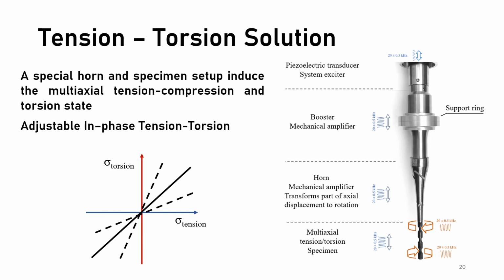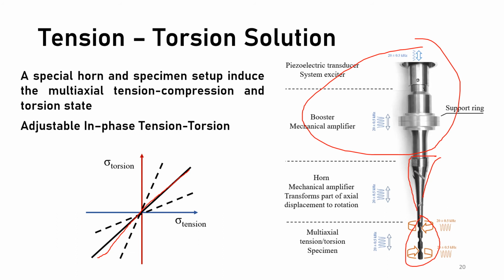Now, the second biaxial very high cycle fatigue method applied is the tension-torsion solution, developed by our team. We apply the same piezoelectric transducer exciter to the same booster, but we change to a special horn that not only excites the specimen in an axial displacement, but also provides a rotation displacement, thus exciting the specimen in both an axial and a rotational resonance mode, achieving an in-phase tension-torsion stress combination that is adjustable. Here we can easily increase torsion or tension in the relation between tension and torsion.